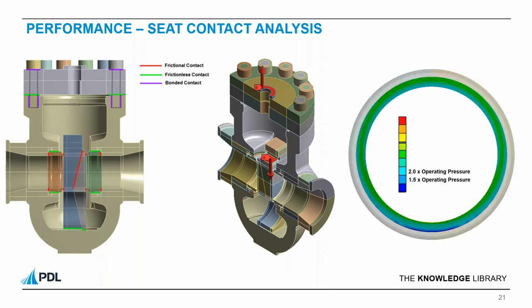The contact pressure between the seat and the gate can be seen here on the right when we've just got actuator forces in only. The contours are set to 2 times the operational pressure and 1.5 times the operational pressure. So you can see that we've got a nice thick band here, and this will be sealing. We did recommend to increase the torque to give a better sealing pressure. And this image is with it increased.